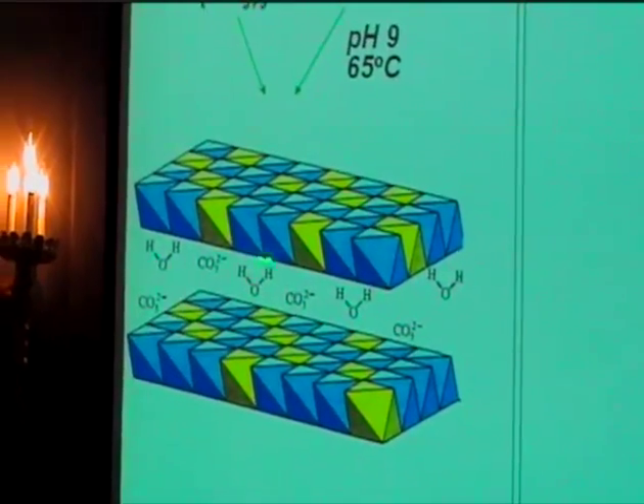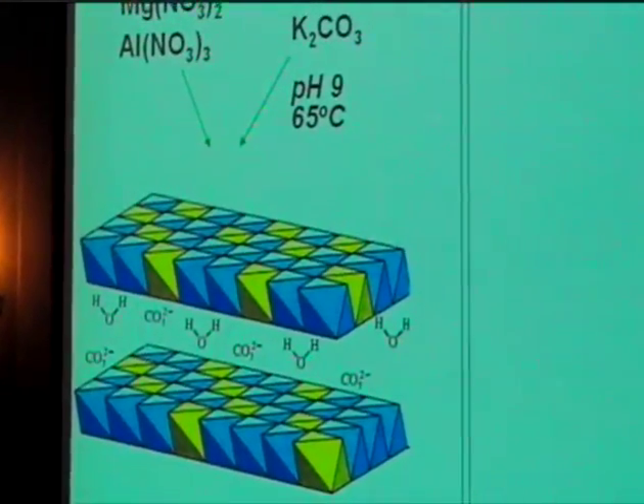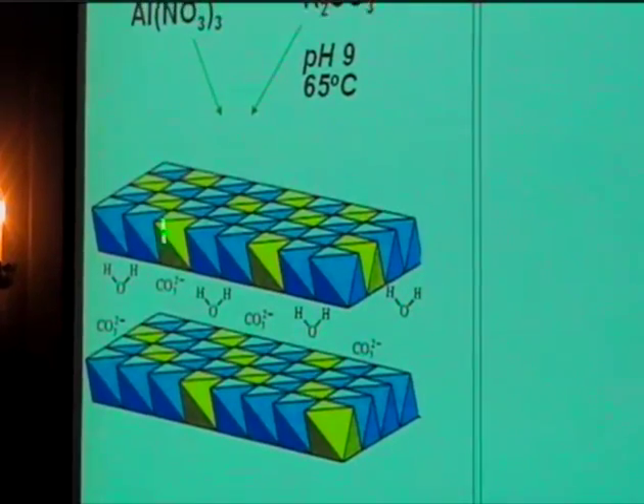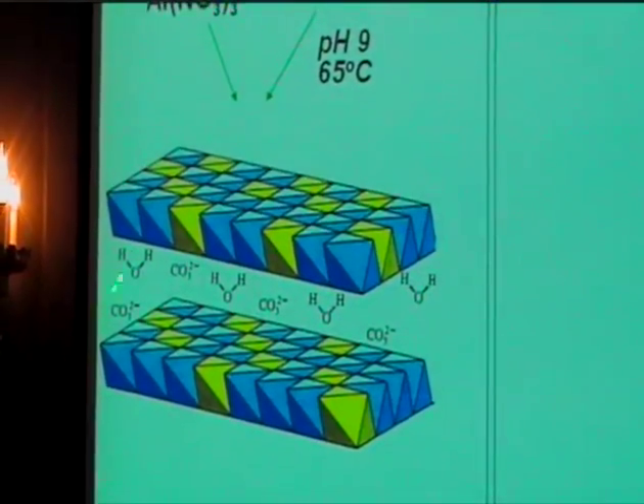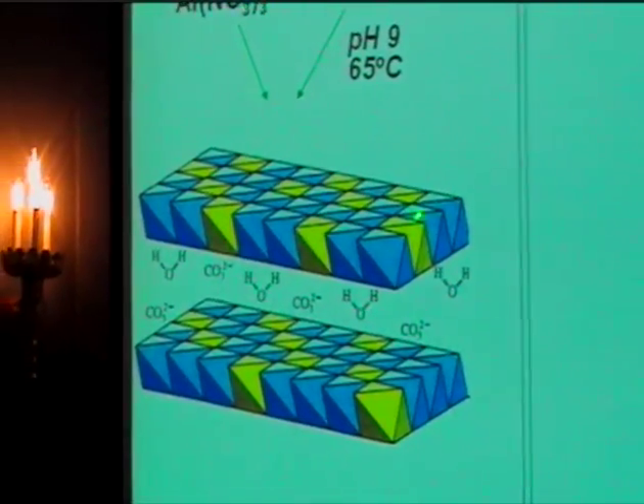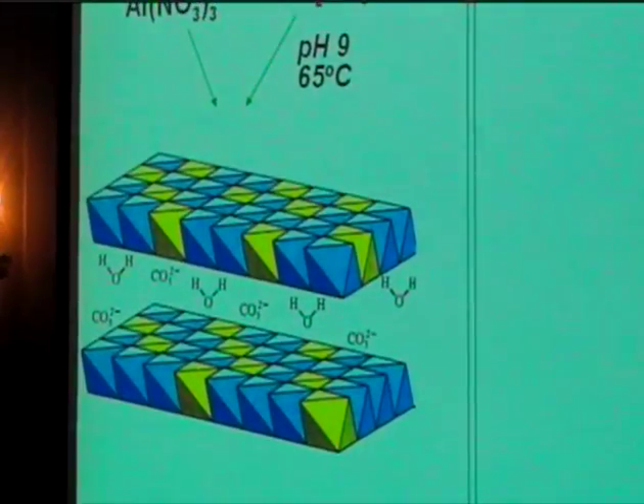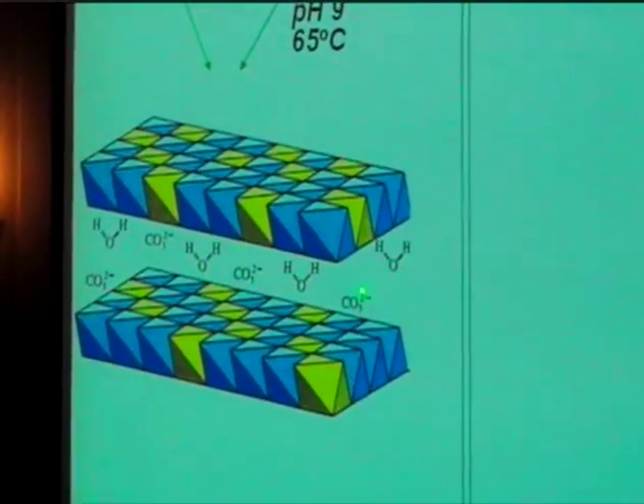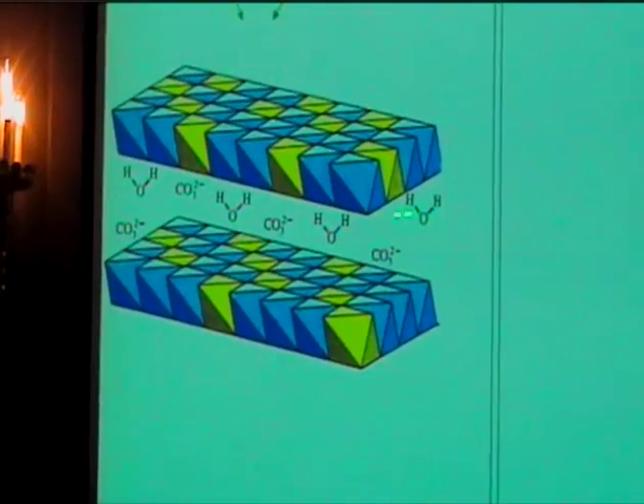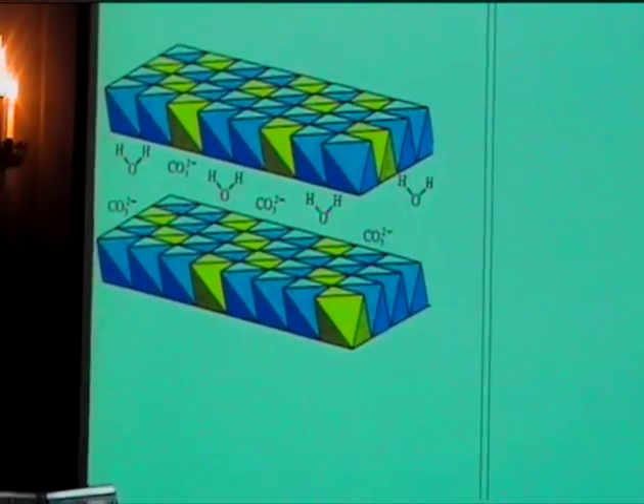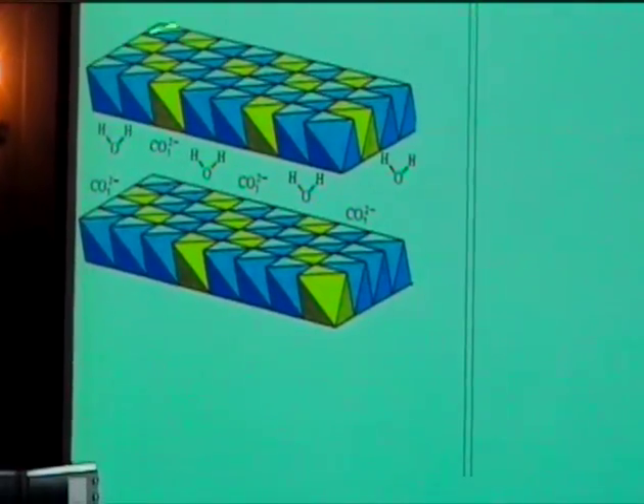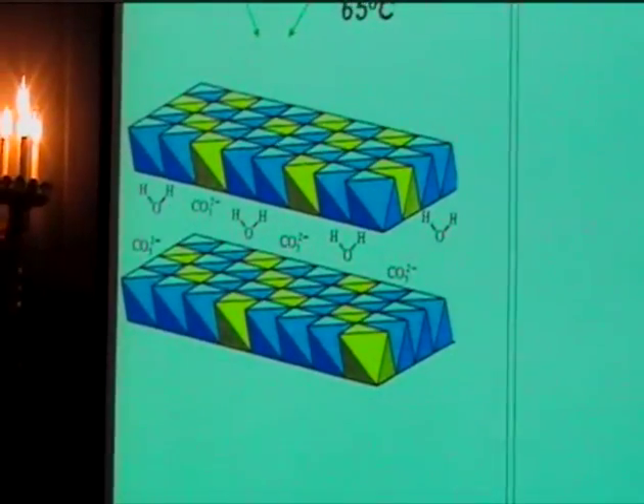They're layers. You can think of them as layers of brucite, or magnesium hydroxide, into which some aluminum has been substituted. Because of that, it creates a positive charge in the layer, the aluminum being +3, replacing the +2 magnesium, and you wind up with carbonate and some water in between these interlayers as a way of neutralizing the positive charge on the surface. Okay, so that's a nice material.